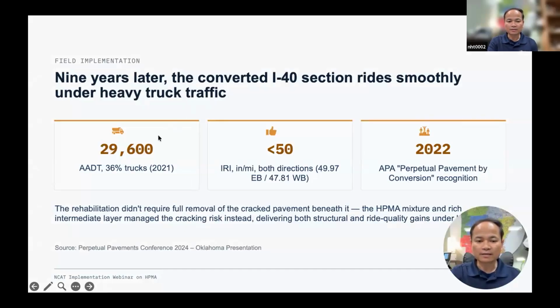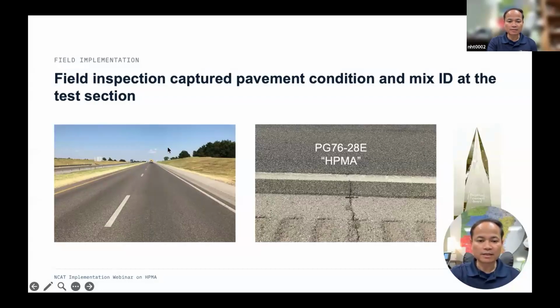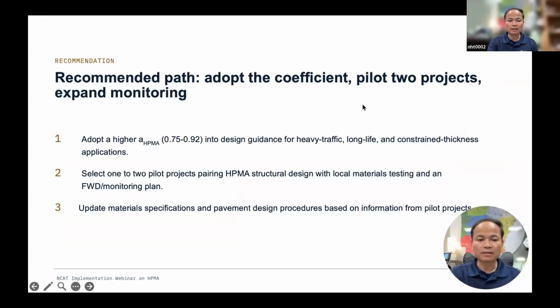Fast forward 9 years later, you can see there is a lot of truck traffic on the section up to 2021. The IRI for that section is still below 50 inches per mile with great performance. And then in 2022, the Asphalt Pavement Alliance gave the Perpetual Pavement Award to the section. You can see here several pictures of that section in 2021. There's no cracking, and you can see that there's reflective cracking on the shoulder using the conventional mix, and then that reflective cracking stops when it goes into the HPMA mix. This one in this case is PG 76-28E, and next to that is the Perpetual Pavement Award presented by APA.